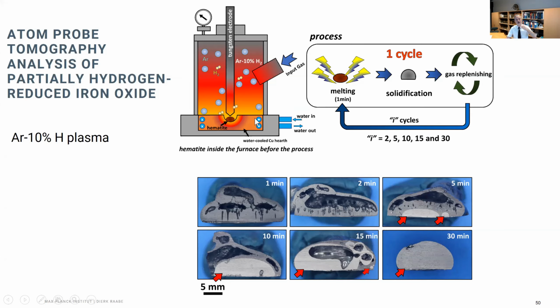And then you can, in a very well-defined setting and sequence of melts, expose that ore to the plasma, ignite the plasma, start melting it, and then you not only reduce the oxide in the liquid state, the melting point of that oxide is not much higher than that of iron, so you work in a similar ballpark, but you also lose some of the oxygen already through the vapor pressure. So it's a very, very efficient process, and we are currently only starting to scratch the surface.